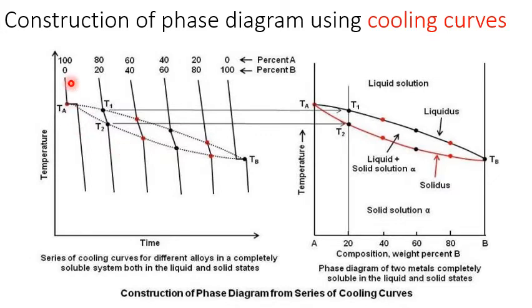you can see, starts freezing at a temperature called the freezing temperature, and the temperature remains constant, and then the temperature starts decreasing. But when we have a mixture of two components, the temperature will not remain constant. Why? Because A may start solidifying at a temperature different from B. So the latent heat of fusion will give a slope. It's not a straight line. It will not remain constant.